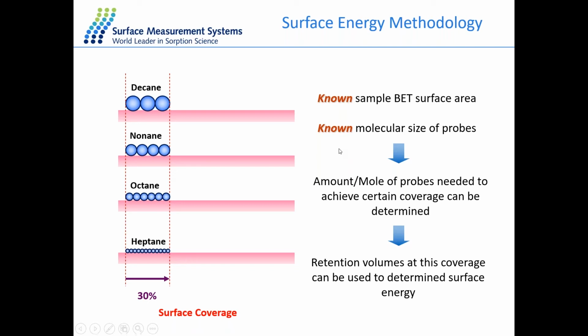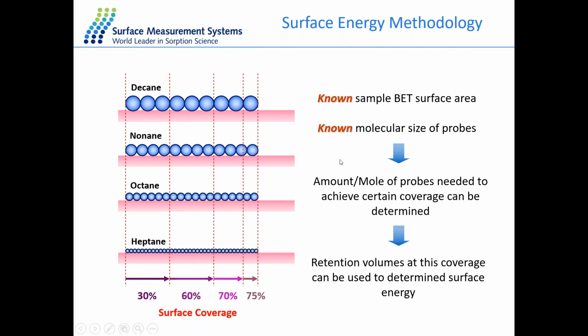As I showed before, we have a nice database of the probe molecules available, calibrated in our system, and we also have their physical properties. So these are the two things we need to know. What we can then go ahead and do is use software to calculate the amount of moles or percentage of the probes that we need to achieve a certain coverage of the surface of your sample. Then we can go ahead and start the experiment.